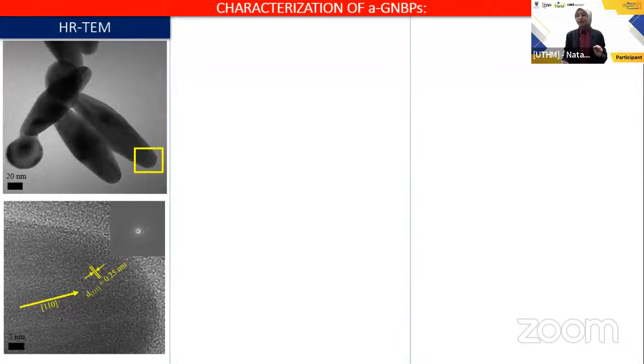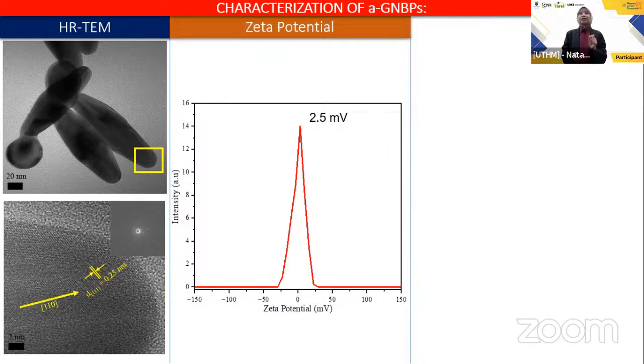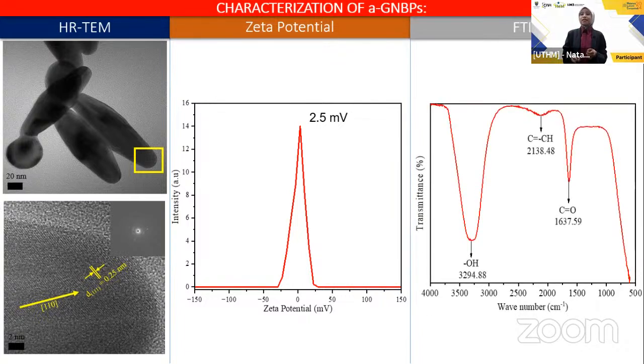Next, we have TEM here. Based on these results, the tip and slope angles of A-GNBPS are 1.01 times higher than pure GNBPS, which indicates an initiation of the surface scraping phenomenon conducted by amine groups that allows for the morphological change. With a zeta potential value measured at 2.5 millivolts, which is increased from pure GNBPS, and the last one is FTIR. We obtain that the utilization of amine groups to modify the surface of gold nanobipyramids can influence the wave number shift. Next, let's move on to T-GNBPS, or thiol functionalized GNBPS.